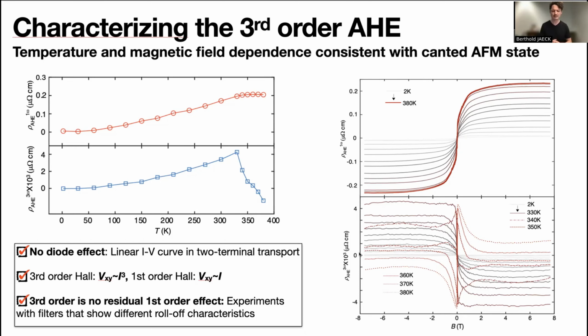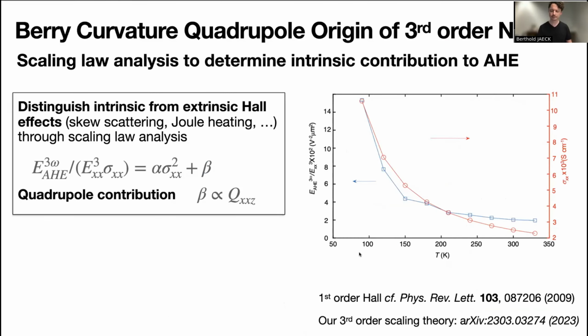The question that now arises, how can we identify the origin of this third order Hall response? It's seemingly consistent with our toy model, but what can we do here? Well, the best thing we can try to convince you that this is coming from a Berry curvature quadrupole is to set up a so-called scaling theory. The idea behind these scaling theories, which now have been around for maybe 15 years or more, is that there is essentially a scaling relation between the Hall conductivity and the longitudinal conductivity.